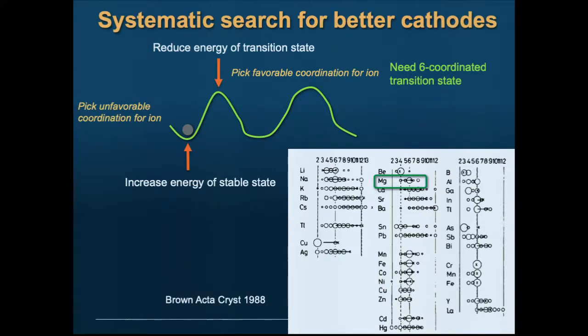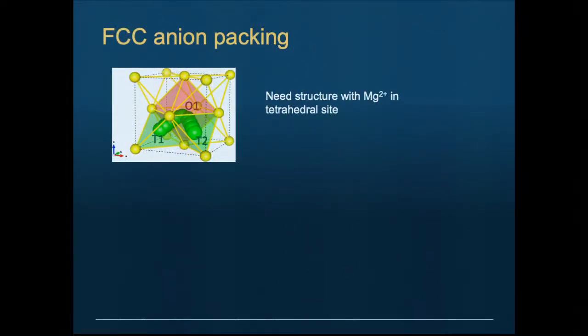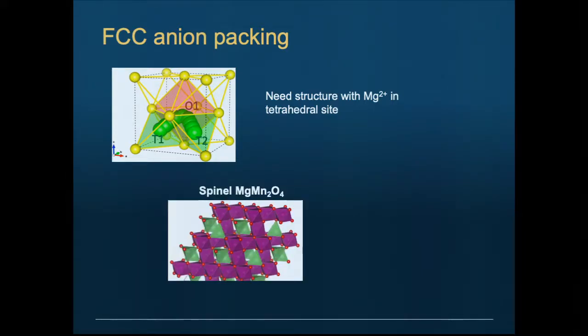Duh, some old-style ceramists among you will say, that's a spinel, right? In spinel, you push one of the ions into a tetrahedral site, even when it prefers to be octahedral, and because the spinel is an FCC oxygen packing, to diffuse from one tetrahedral site to the other one, you have to go through the octahedral site. So this is perfect for magnesium, because magnesium prefers octahedral, but in spinel it's pushed to tetrahedral. So it's going to sit in a slightly unhappy site, and then as it diffuses through, it becomes happier. So you get a chance to bring down the activated state.